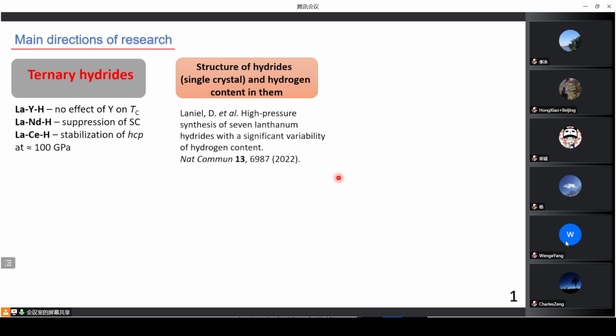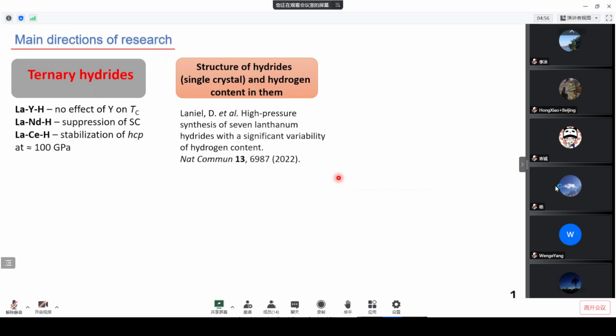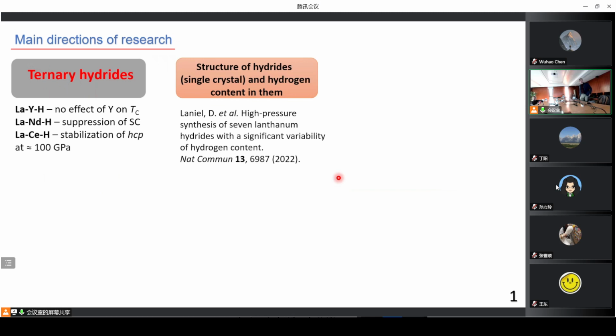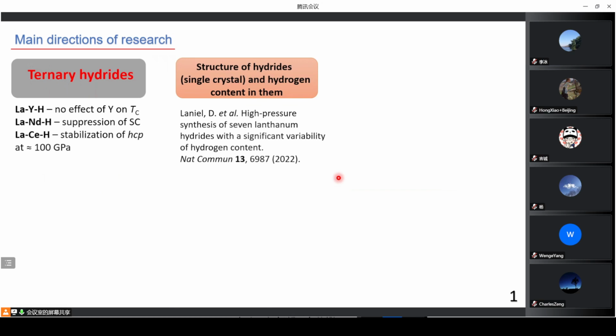The next direction was, let's say, opened by a group of Dubrovinsky from Bayreuth University. They developed single crystal X-ray diffraction methods for diamond cells, and we can now get the exact position of heavy atoms, and in some cases even hydrogen atoms in polyhydrides at high pressure up to 200 GPa at least.